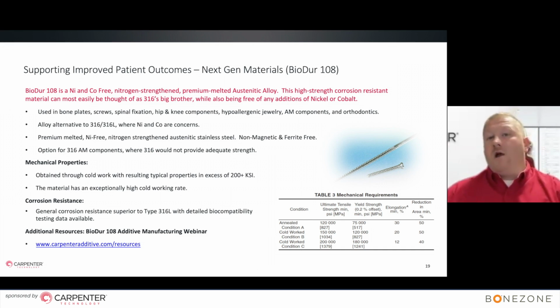This particular alloy I consider as the big brother to 316 LVM stainless, and it allows for increased strength through cold work because it is a purely austenitic material. And it essentially has 0 nickel content and 0 cobalt. And in its powder form, it has printability for additive manufacturing. So something pretty unique about the product.